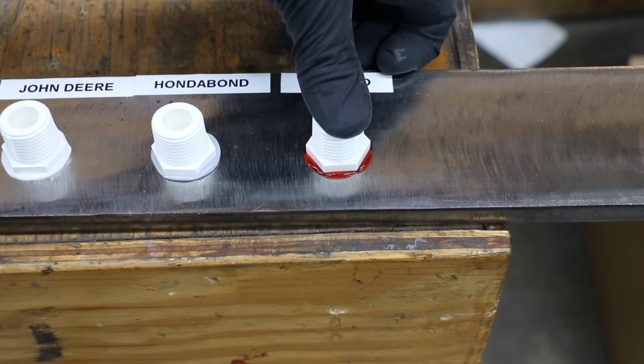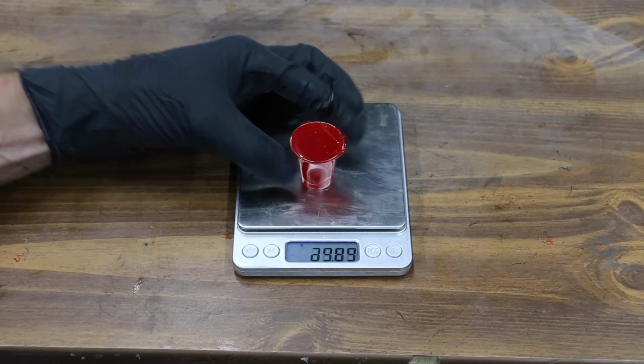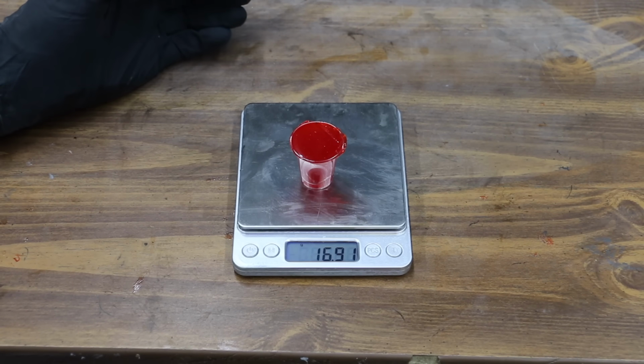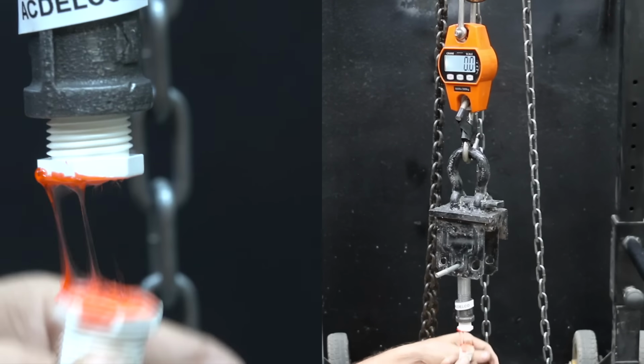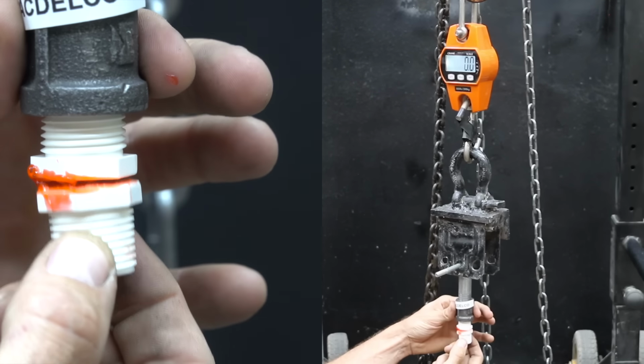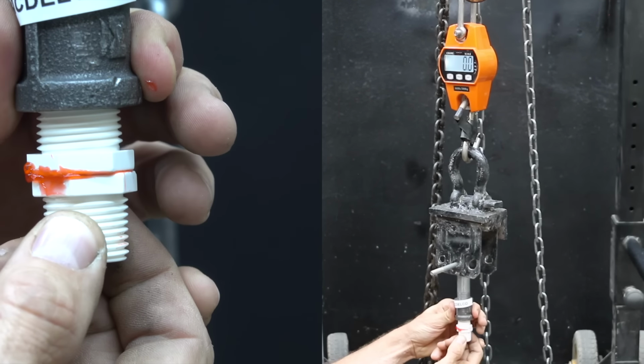There's no information on the packaging regarding where the AC Delco is made, and the AC Delco is pretty light at 16.91 grams. And the AC Delco claims to cure between close-fitting surfaces, but the AC Delco is very gooey across the entire test piece.